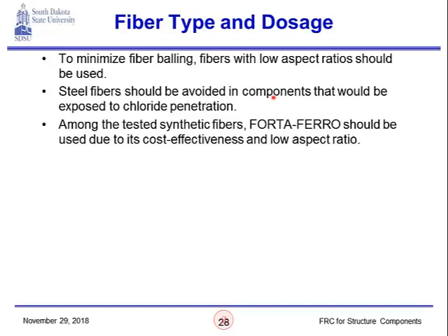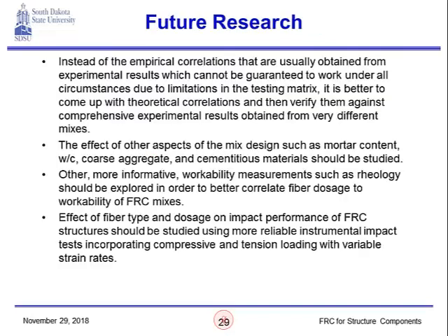Steel fibers should be avoided in components that would be exposed to chloride penetration. So this is basically why steel fibers are usually not used in applications where we have very harsh winters. And so these are the summary of the recommendations. A more detailed guideline that we provided for South Dakota DOT could be found in the report that was submitted to both MPC and South Dakota DOT, which should be, as I said, attached in this webinar.